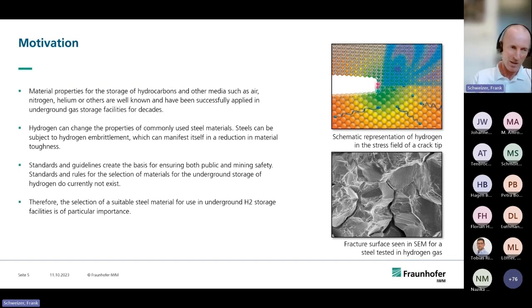There are also other materials, but we have focused on the steel materials. As you see on the right side, there's a schematic representation of hydrogen, and you see if there are small or micro cracks forming on the surface, you get stress fields around this, and the hydrogen will diffuse there, and also if it gets to the crack tip, the atoms will separate. There will be a decohesion, or there could be a decohesion. And in the absolute worst case, there could be a fracture, as you see in the lower picture.